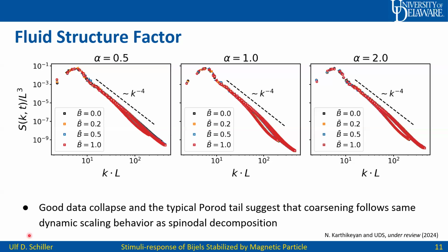That goes back to the idea that it's challenging to form bijels. What this means is essentially the formation is still mostly driven by spinodal decomposition. So adding the particles does not fundamentally alter the mechanism with which the phase separation occurs, which is interesting because it suggests that experimentally this will not be a problem.